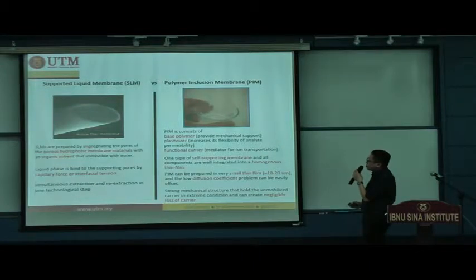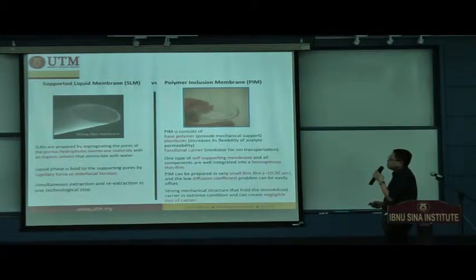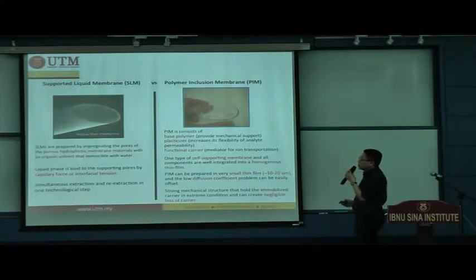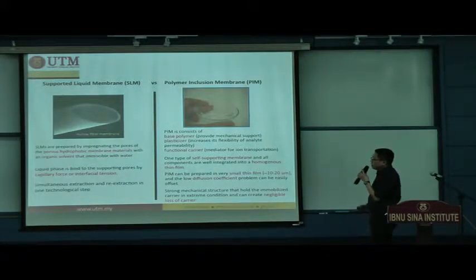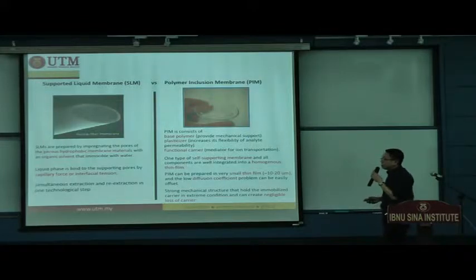The supported liquid membrane is prepared by impregnating the pores of the porous hydrophobic membrane material with an organic solvent that is immiscible with water. The liquid phase is bound to the supporting pores by capillary force or interfacial tension. This kind of binding energy is very weak and not stable, especially when you are working in highly agitated solutions. The advantage is that the entire procedure is a simultaneous extraction and re-extraction in one technological step.